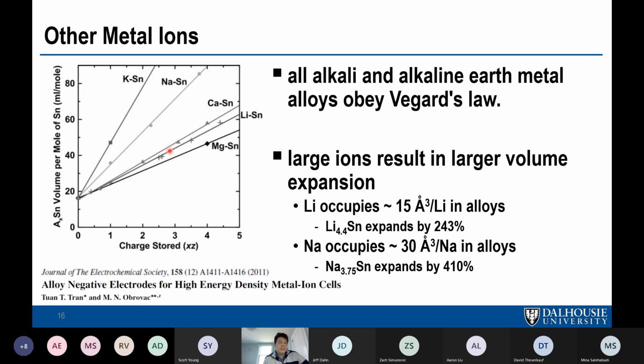And you could see for some ions, they have greater volume expansion than lithium because the size of the atoms per charge is bigger. Magnesium is attractive. It got a lot of attention because the size of magnesium is smaller per unit charge than lithium, and so you get less volume expansion per unit charge. And as an example, when you're inserting sodium in an alloy, you should expect about double the volume expansion as lithium, because the size of the sodium atom in alloys is twice that of lithium.